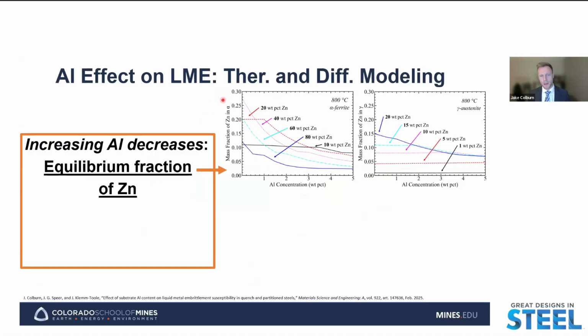And so here we have calculated the mass fraction of zinc in those substrate phases at 800 degrees C for increasing aluminum concentration at different zinc concentrations in the substrate. And the main trend that we see here is that as we increase the aluminum concentration in the substrate or at that interface, we see a decrease in the mass fraction of zinc in the substrate, or essentially what the maximum solubility of zinc in the substrate would be. We see a decrease with increasing aluminum content.